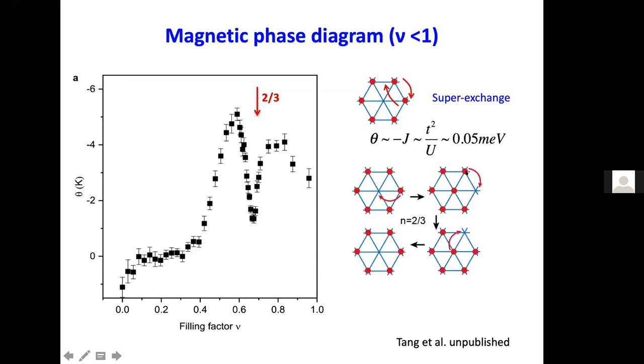But there's another channel: for example, this particle can hop into the middle empty seat, then this guy can take over this seat, and then this can go back. Effectively, by doing something like this, those two particles have already completed an exchange, and the potential energy involved is V instead of U. So then you can get a little bit higher interaction energy.